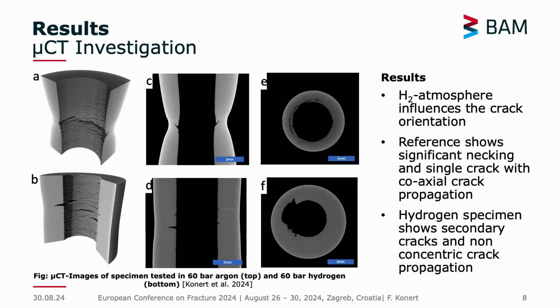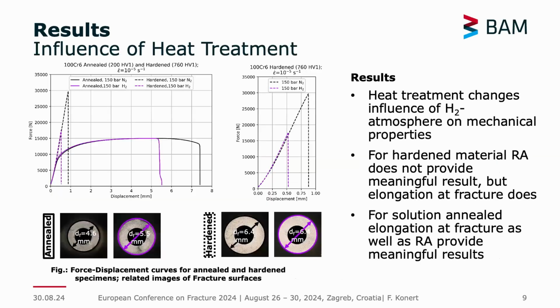In contrast, in the hydrogen-charged specimen, you have a different orientation. It's 90 degrees to the loading axis, and you also see that the crack does not go really concentrically from the inner center of the hole. We see this for some materials, and I guess a lot of people also saw this in the presentation of Yannick, I think it was yesterday, for this wire arc deposited specimen.